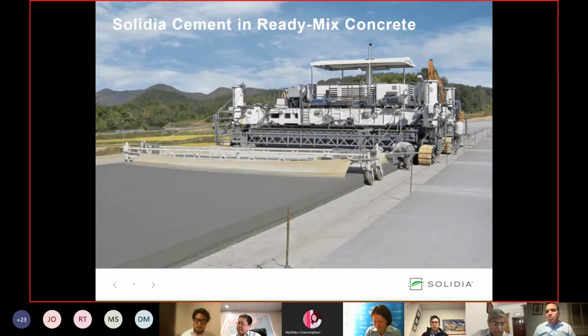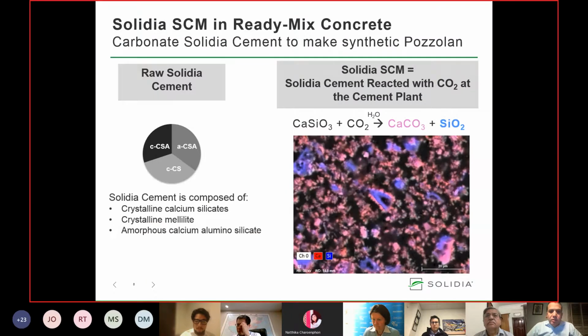So how do we tackle this problem? With the precast, we need to carbonate it, and in order to carbonate it, we need a chamber to put our concrete in and process it. But in the field, this is not really practical, so we had to find a solution for this. Our solution is carbonating Solidia cement in the powder form and using it as a supplementary cementitious material. When you look at Solidia cement, it's really composed of three major phases: the crystalline calcium silicates, the crystalline melilite group, and also amorphous calcium aluminosilicates.